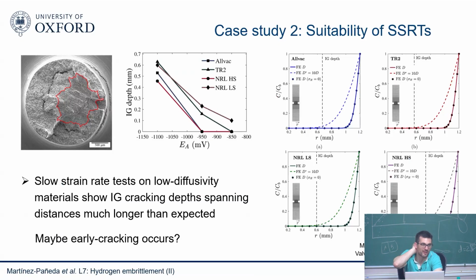First, what we did was numerical simulations of hydrogen transport. So what you see here is the hydrogen concentration normalized by the boundary value. So this is the edge of my component, for the four materials that we considered, four types of nickel superalloys. This is the finite element predictions. They wanted to see whether the hydrostatic stress made a big difference, but it didn't. But anyway, the solid lines are the predictions for the real diffusivity of the material. This black dashed line is the degree of intergranular depth that they measure in the experiments.